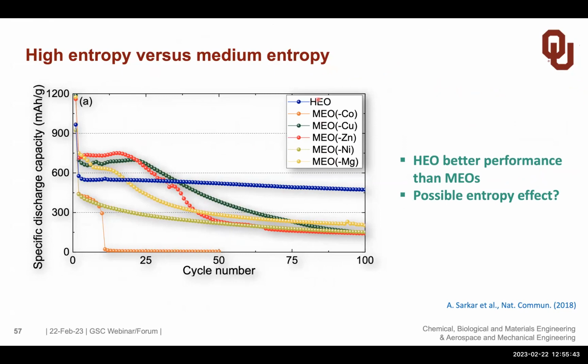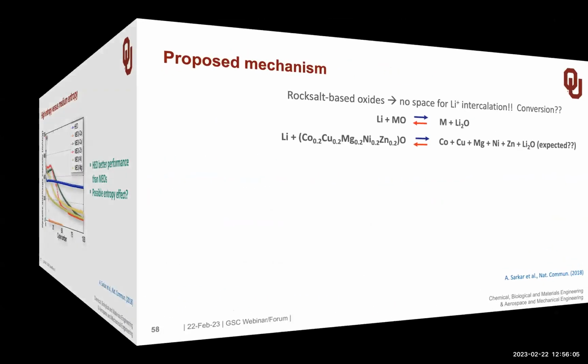The interesting part, from a scientific point of view, is that if you look at the performance of a high entropy oxide in this application, it has a good stability. But if you take any of the other transition elements out, for example, the cobalt or the copper or the zinc, you see that the material decays. So it seems that the high entropy is important to stabilize the cycling behavior.